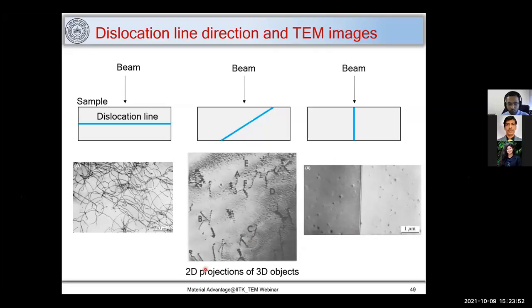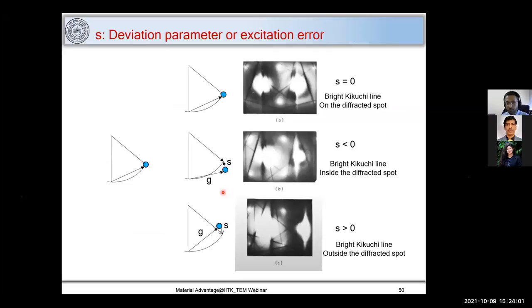Mind you, you are seeing 2D projections of 3D objects. So you can interpret how dislocations are aligned with respect to the beam by just looking at the micrographs. Now I would like you to pay attention. Here we talked about the Kikuchi lines, the Ewald sphere and a G vector, which is marked here. Here there is no deviation parameter. S is 0 here. This is G, and this condition is obtained when we go to the two beam condition. Here is our Kikuchi line, which goes through the center of the spot where S is equal to 0.